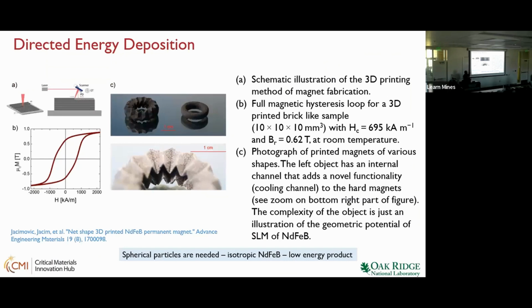So when we started working on metal additive, for all the laser additive processes, you need a spherical particle. The moment you go to spherical particles, mostly you will end up with isotropic magnets. The isotropic magnets are very weak. So that's why we cannot do it right now. Initially ABB worked on some of these things, and we have done some work also. So you are going to make a porous magnet, and there are some improvements they are making, but it's not there yet. So it's still a weaker magnet.